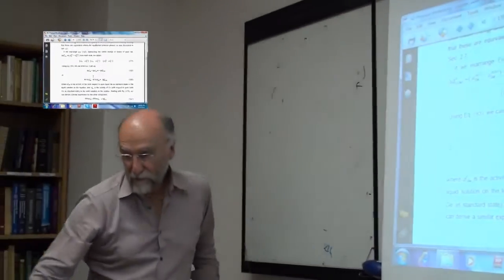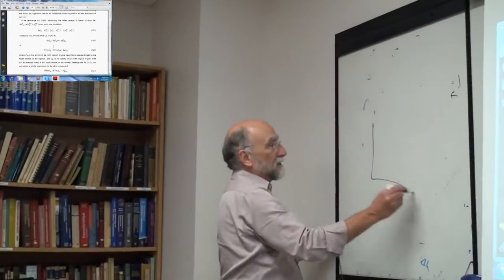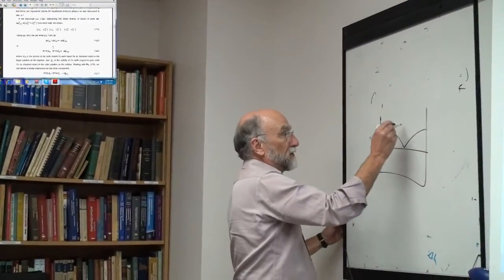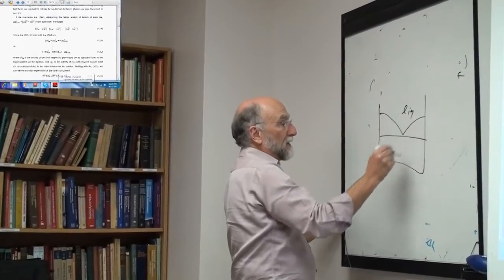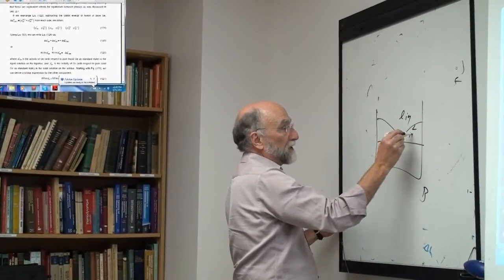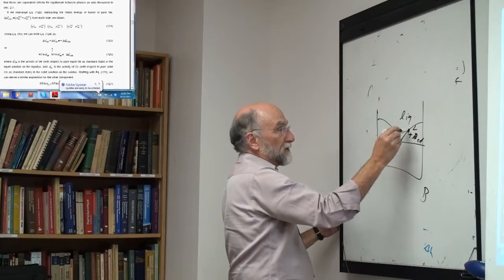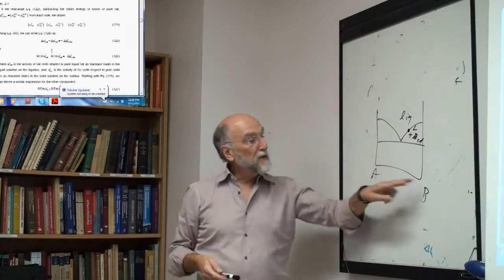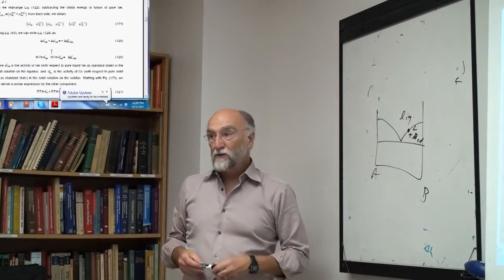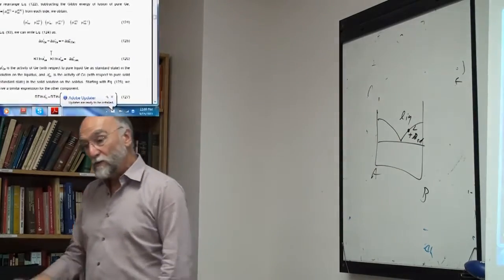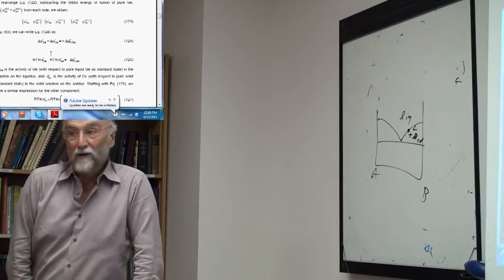And I've had people say the same thing. Say you take a eutectic diagram. Here you have liquid, here you have liquid plus A, solid, or B, sorry, B, solid. And here you're on the liquidus, so you say, well, at this point on the liquidus, the activity of B is 1, because it's in equilibrium with pure solid, so the activity of B on the liquidus must be 1. Well, no, the activity of B on the liquidus is equal to 1 with respect to the solid standard state, but is not equal to 1 with respect to the liquid standard state.